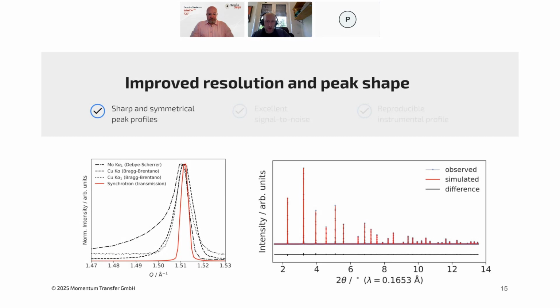This can be modeled and corrected for, but it generally reduces your ability to resolve shoulder peaks or peaks that are very close together underneath that curve. And the other thing is this very symmetrical and sharp profile makes it much easier to model the data. And so we can get very good refinements of any structure phases from, for instance, Rietveld refinement.